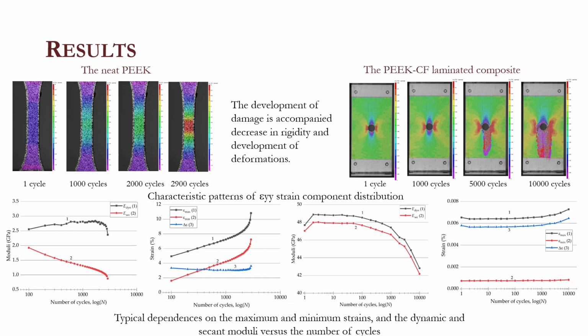The slide shows characteristic patterns of the eyy strain component distribution and typical dependencies of the maximum and minimum strains, and the dynamic and secant moduli versus the number of cycles. It is shown that the development of damage is accompanied by a decrease in rigidity and development of deformations.